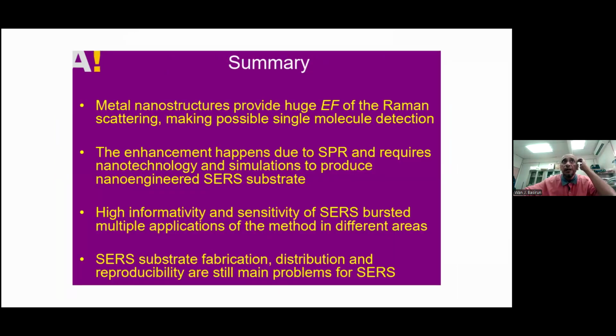So summary basically, metal nanostructures provide huge electromagnetic enhancement for Raman scattering, making single molecule detection possible. So meaning when you have SERS, when you have the metal surface bonded with even a single molecule, that will actually make detection possible because the enhancement is very, very huge, at 10 power 14. So this enhancement happens due to SPR, surface plasmon resonance, which actually combined with the laser and the radiation to get a very high signal enhancement from the SERS effect.